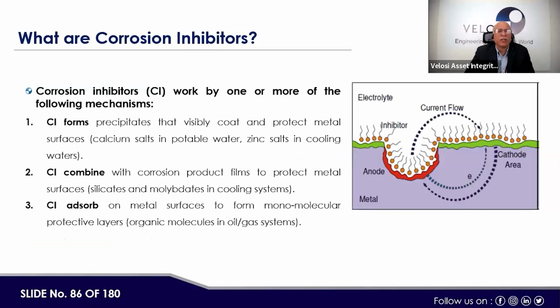Now, there are corrosion inhibitors. If you know from the corrosion background, there are various corrosion inhibitors which are used for internal corrosion, like methanol or glycol based, or methanol injection for prevention of hydrate formation, and then another inhibitor to minimize CO2 or H2S based corrosion. So these corrosion inhibitors are of three types. One forms a precipitate that visibly coats and protects metal surfaces. The corrosion inhibitors are mostly used for the internal part, not for the external part, and are injected with the process fluid or with a gas.